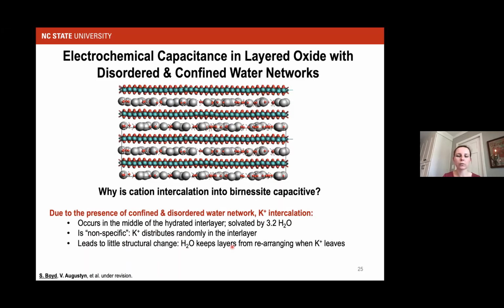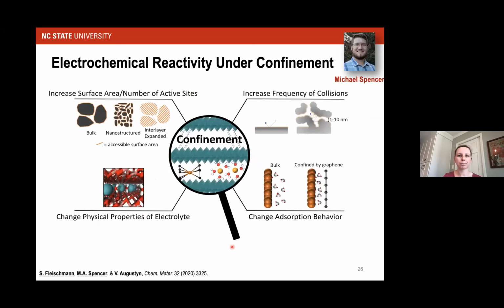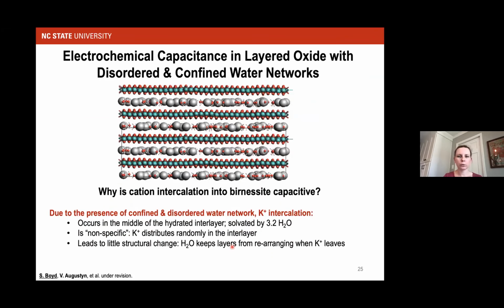So if you remember in our first study with the bulk sodium metal oxides, we found that once the water was present in between the layers, we no longer had that potential dependence of the cyclic voltammetry. So that kind of concludes our story on the very interesting aqueous electrochemistry of manganese oxides and the critical role of water in understanding their capacitive response.